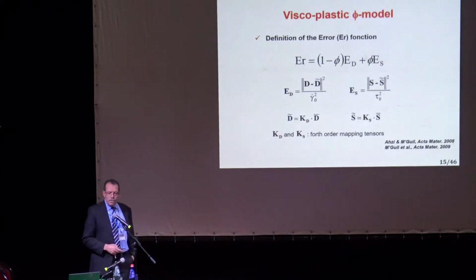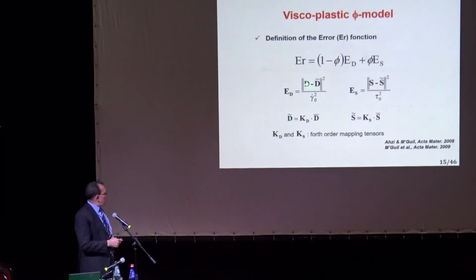If you use upper bound, then you have a huge error in the stresses. If you use lower bound, then you have a huge error in the local strain rates or strains. So we took an error in strain or strain rates, an error in these are quadratics, and then we combined them with this weight function between 0 and 1, the phi, and we call this the phi model.